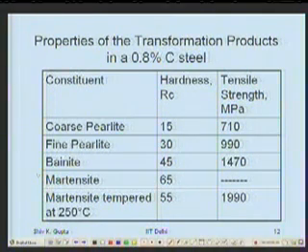But the tensile strength, I am not able to measure because it falls within its elastic limit. It doesn't even reach the yield strength, it's a brittle material. That's what I want to get rid of. For that, we temper the martensite: after transforming the steel to martensite by quenching, we keep it at an elevated temperature. It could be anywhere above room temperature up to about 400 degrees centigrade.